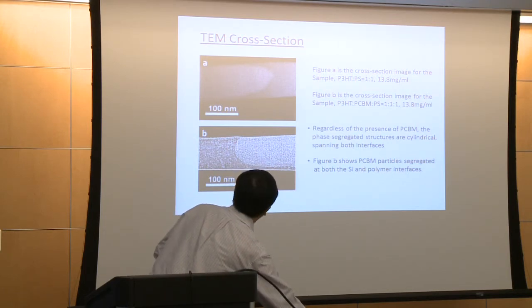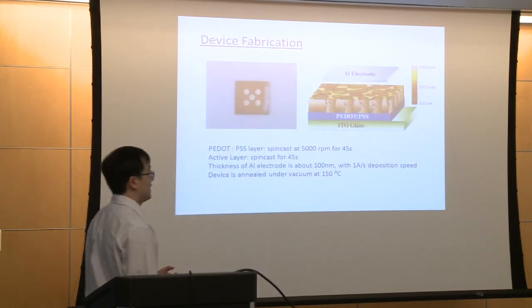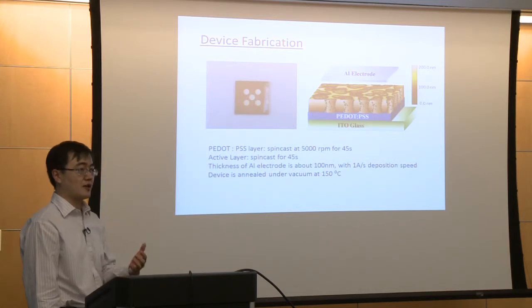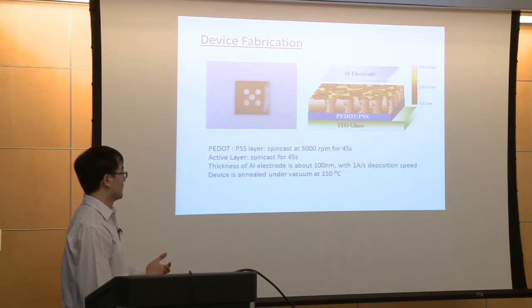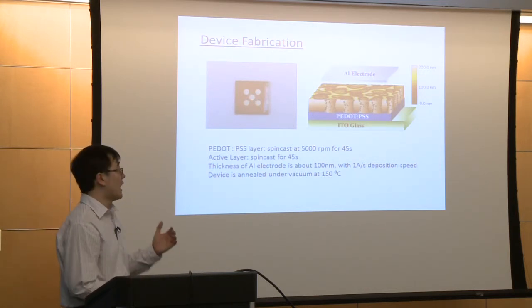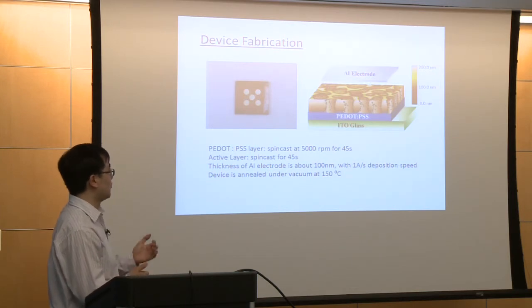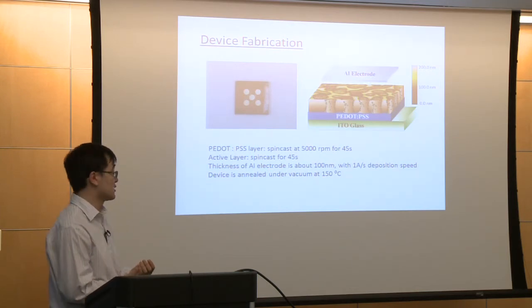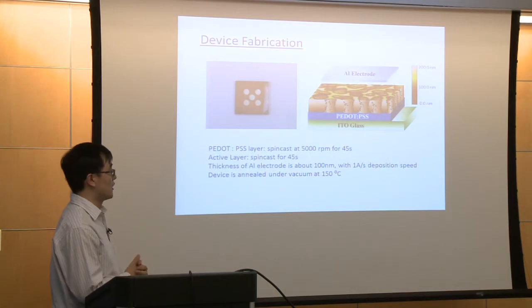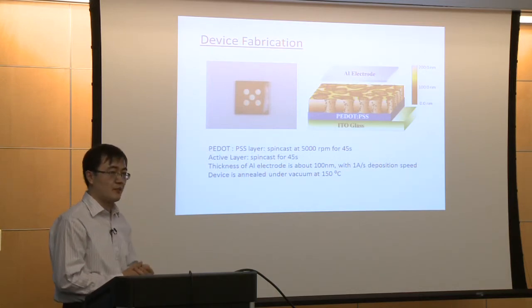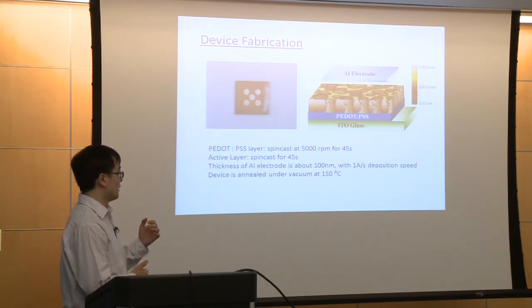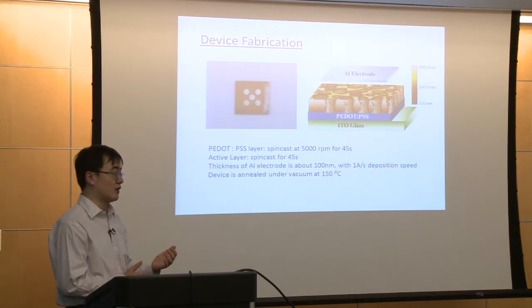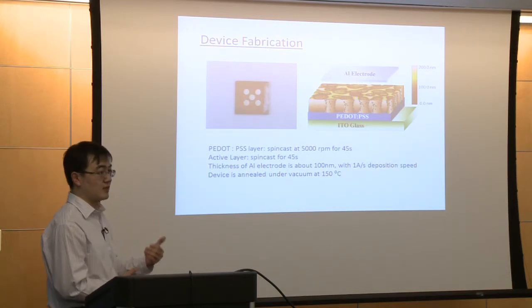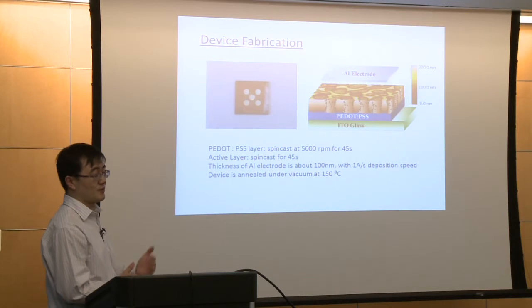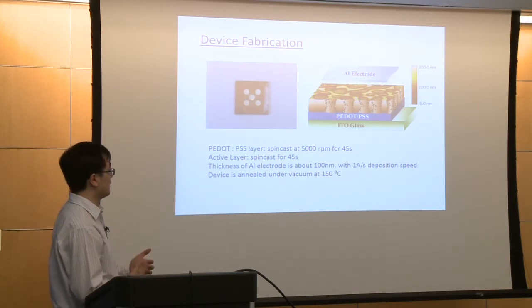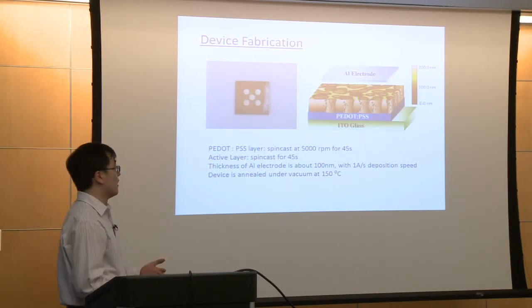So by this TEM cross-section, we can confirm the column structure really formed by our method. So far, we have the theoretical simulation, we have the neutron data, and we have the AFM and TEM data, which can confirm the aggregation of the PCBM along the interface. And we also use TEM cross-section to help us determine the column structure.